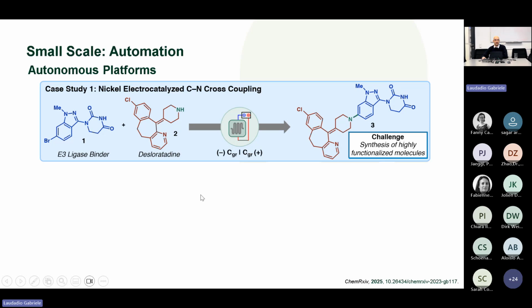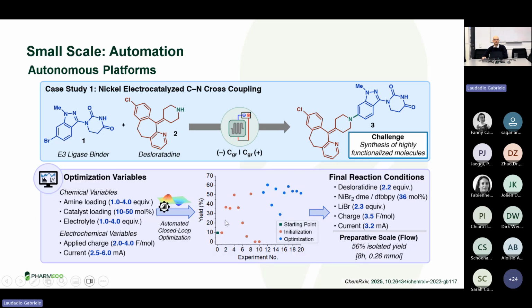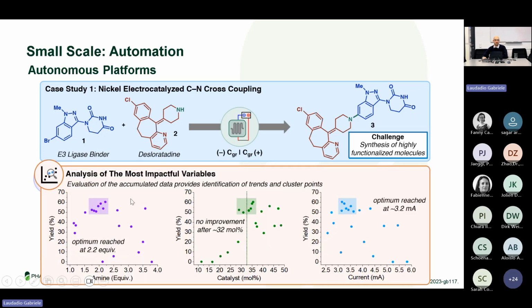So we did, again, this CN electrocatalyzed cross-coupling. And we ran our Bayesian optimization where basically the new reaction conditions could be identified in terms of optimization. We isolated the compound by scaling up these conditions. And also we could observe very interesting trends based on the Bayesian optimization campaign. For example, we could identify the optimal nickel amounts or the optimal current that should be used and so on.